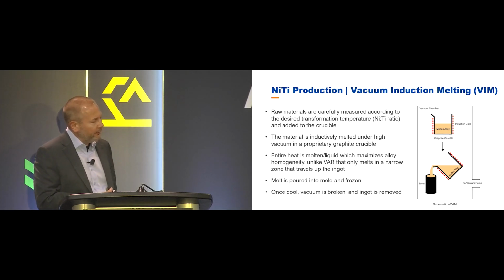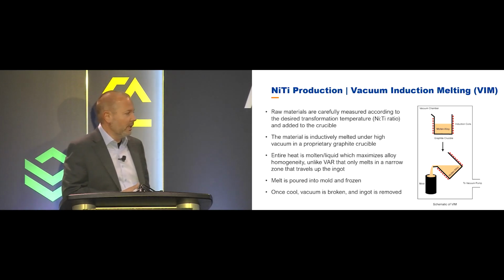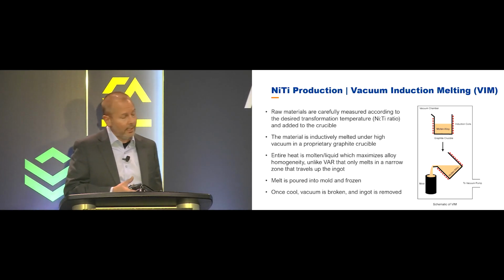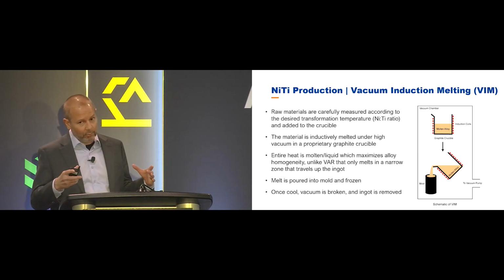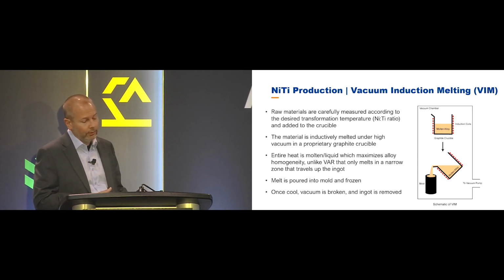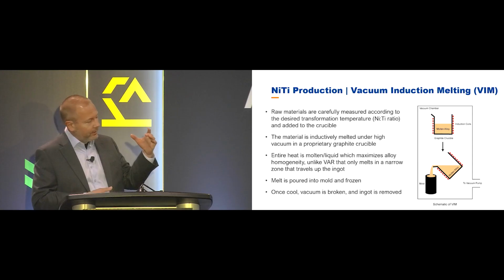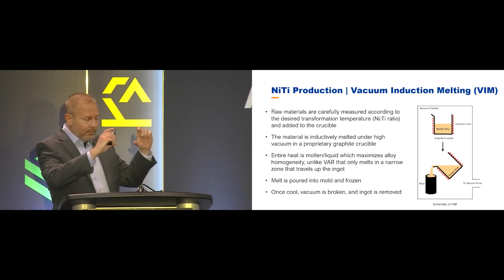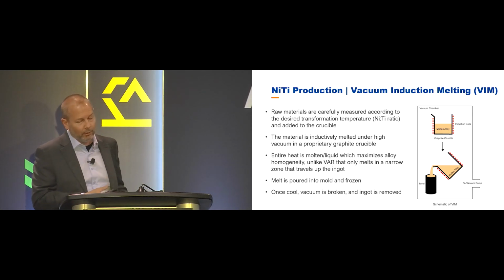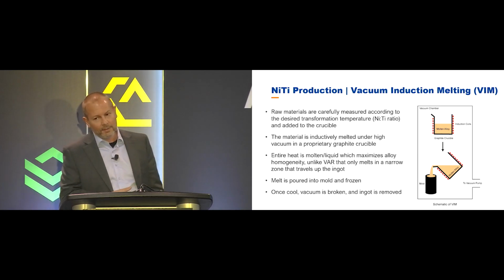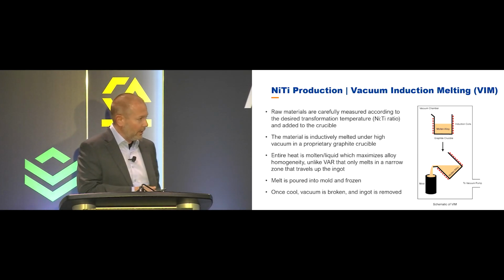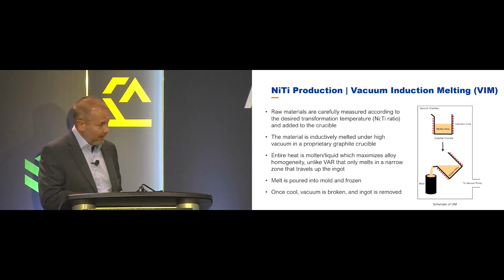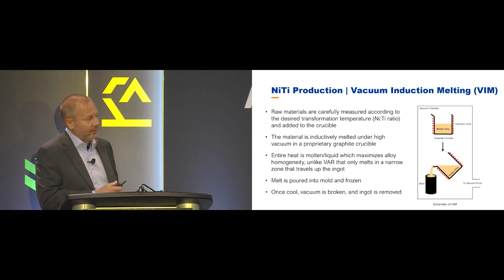So the other advantage to doing this, or the main advantage to doing it, is everything is molten at the same time. Other melt practices, you might melt through a zone. If you have a direct VAR, revar, you compress a briquette of material, the same form of raw material I showed you earlier, and you apply current to it, and you melt, and you have a zone that's molten. So you have to remelt to try and get better homogeneity, whereas here, everything's molten at the same time. There's some currents in the crucible, which gets some mixing as well from the induction field.